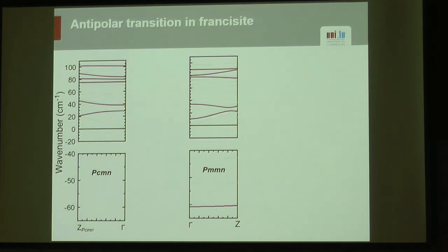We have also highlighted here in pink the branches that correspond to the fully symmetric modes that we would typically see in Raman spectroscopy. The soft mode we're interested in comes from here, and if you look at the eigenvector, it's essentially chlorine moving in an anti-parallel fashion. This is why people have been arguing that this transition can be seen as being driven only by this chlorine motion.